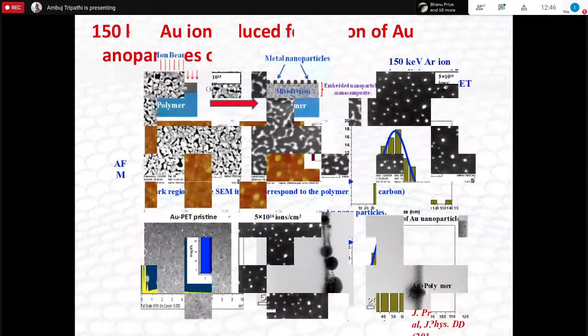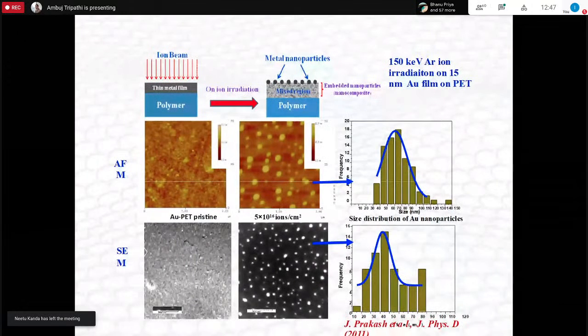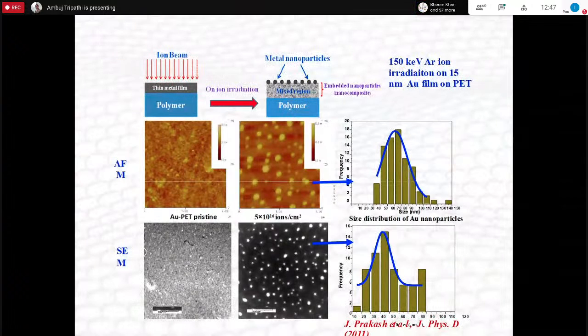And when you are doing all this analysis, one slide I sometimes include to show you that this is interesting is that in AFM and SEM, if you look at the same thing, you will find that sizes are different. So these are the measurement techniques, what you measure with different systems. You will see the size distribution, AFM is showing slightly higher, though the same sample is studied with AFM and SEM. So those are about the different techniques. You have to always keep in mind, when you are doing all these measurements, that you should know the limitation of the technique you are using, because what you see may not be exactly what is there.